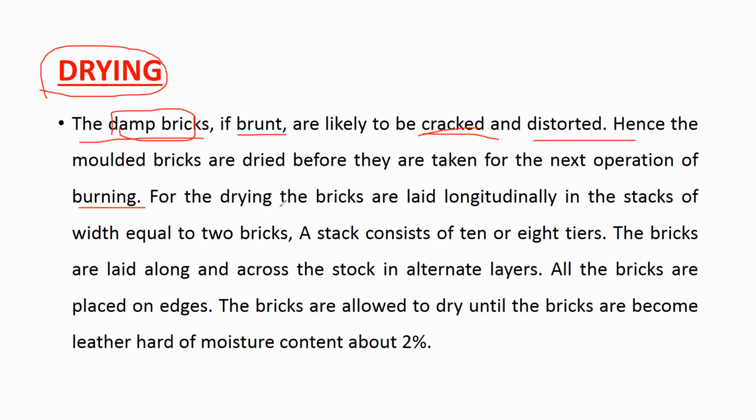For the drying, the bricks are laid longitudinally in the stack with a width equal to 2 bricks. A stack consists of 10 or 8 tiers. The bricks are laid along and across the stack in alternate layers. All the bricks are placed on edges. The bricks are allowed to dry until they become leather hard, with a moisture content of about 2%.